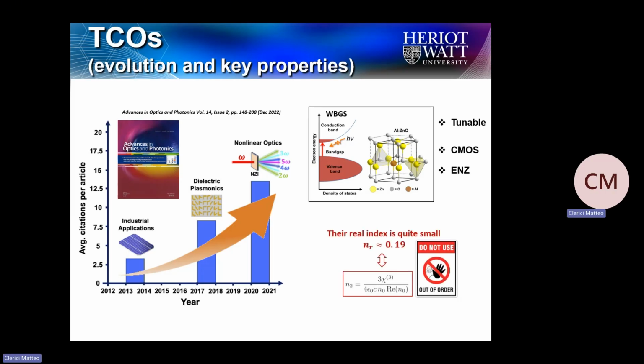Strangely enough, this is a formula that I should not report, but I do it not to upset my colleagues, but fundamentally for two reasons. One, because the original intuition that materials with a very low refractive index can be a good alternative in nonlinear optics came from looking at the simple Boyd textbook formula linking the nonlinear Kerr coefficient with the chi3, where you see that the index appears at the denominator, and so when it is small, you can imagine that the nonlinear Kerr coefficient becomes quite large.